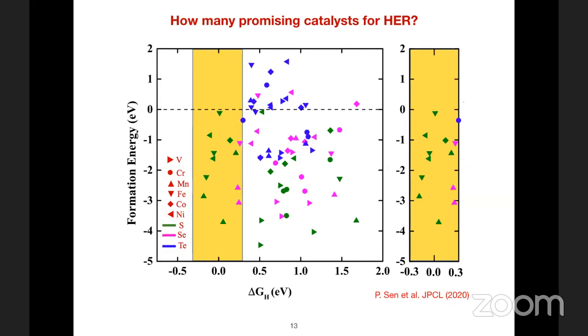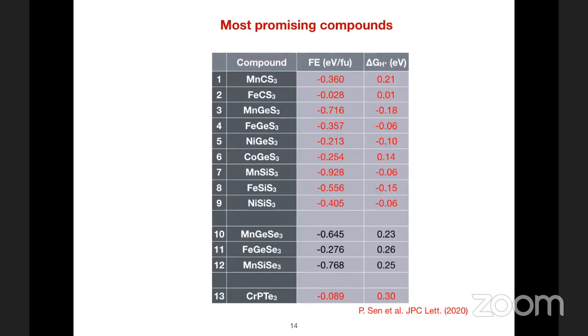So if you count, there are 13 such compounds within this window. So we have 13 compounds that look promising as catalysts for the hydrogen evolution reaction. So these are those 13 compounds. They all have, of course, negative formation energy and delta GH within the range minus 0.3 to 0.3. And some of them, nickel silicon sulfide, iron carbon sulfide, for example, look very, very promising.